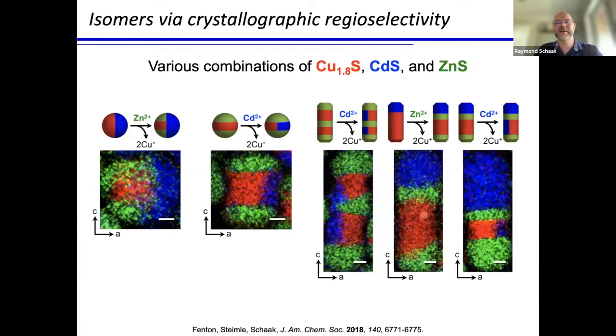And so using those guidelines, we could actually start designing transformation pathways that allowed exquisite placement of three materials within a nanoparticle. And so the result in these cases are spherical particles that have these subtly different arrangements of materials, and these rods that have those same materials integrated in different ways. Those are essentially 5 different nanoparticle isomers of copper sulfide, cadmium sulfide, and zinc sulfide, where the locations of the materials within the particle correlate to the crystallography, the crystal structure relationship. So we think about this as regioselectivity that is defined by crystallographic relationships.